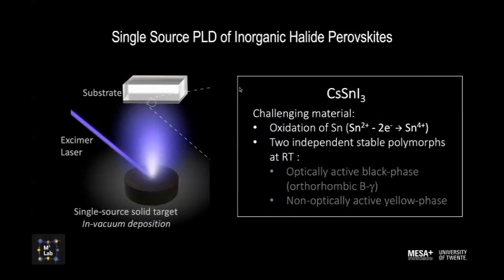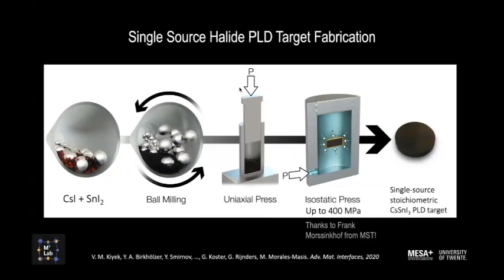So there are two phases that are possible. The one is a non-optically active material. Obviously, that's not the polymorph that you want. You want the black phase, the orthorhombic gamma phase. Depositions were done using pulsed laser deposition with this single source. What was also quite important is that we have a lot of colleagues around in our laboratories who are able to make the right target materials, because if you want to deposit a material using pulsed laser deposition, you need to have the right target with the right composition.